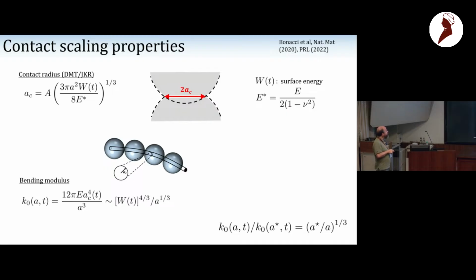The only interest going through the theory here, we are looking at the elastic interaction between two particles. Essentially, the thing to keep in mind is that when you have two particles in contact, there is a small area of contact. And what determines the modulus is essentially this area. It's just a geometric problem where you have two particles in contact on a facet. And so the whole elastic response is determined by the size of the facet. So if you have an evolution of the modulus, you expect that this area of contact will grow. It grows because of the evolution of the adhesive energy.